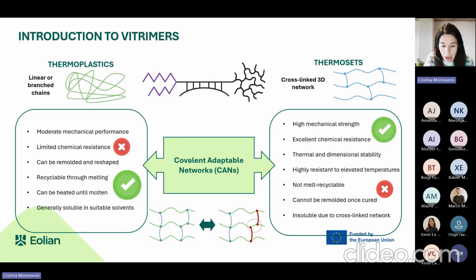Thermosets, on the other hand, behave very differently. During curing, they form irreversible three-dimensional cross-link networks. Once this network is formed, they no longer melt, and if we heat them again, they simply degrade instead of flowing. This gives thermosets excellent heat resistance and dimensional stability, but it also means they are very difficult to recycle.